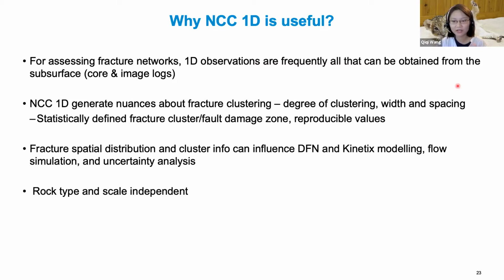For example, Kinetix can only model a 1 mile times 2 miles area with a maximum 100,000 fractures. Thus, in many cases, you may need to simplify your DFN model before feeding it to the kinetic simulation. And once we quantify the principal cluster spacing and the width of the natural fractures from horizontal wellbore, maybe we want to make sure we maintain the trend in our DFN as we simplify it. And in the flow simulation, I would imagine with the same number of total fractures, your DPDK model or your single porosity model would be very different. So for example, if your fracture patterns are super clustered, maybe you can treat your fracture cluster as one bigger fracture instead of many smaller fractures. And also this method is rock type and scale independent. So it can be applied to your tight sandstones, your shale reservoirs, your carbonates.